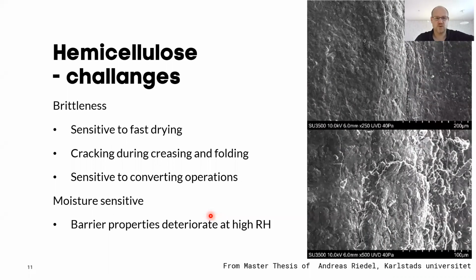The problem we also saw is that you get cracks during converting operations, and these are some images of the surface of hemicellulose. I had a master's thesis student, Andreas Riedel at Karlstad University, who did the work on this, and you can see the cracks here around the creasing line. You have the creasing line there, and you have the cracks just beside it, and this is just a magnification of the whole thing. The problem with these kinds of cracks is that you don't see them with the naked eye or in a light microscope. You need to go to quite high resolution in order to see them, but they are quite harmful when it comes to oxygen barrier properties.